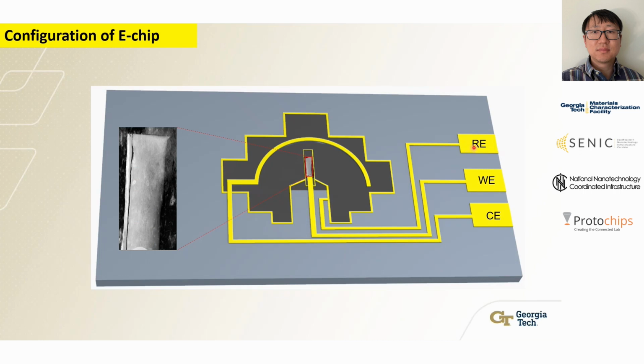There are RE, WE, and CE, which refer to reference electrode, working electrode, and counter electrode. Those electrodes were made of platinum, and our sample was produced by the focused ion beam, the FIB, and is mounted at the end of the working electrode. Of course, the membrane around this sample is the electron transparent silicon nitride.